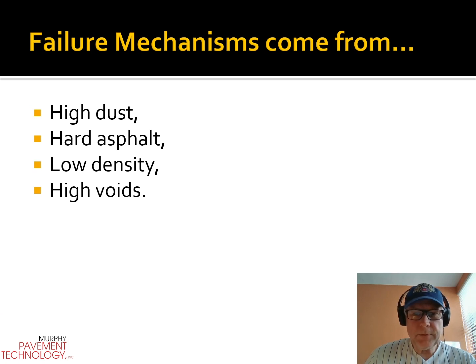So, some summaries again: failure mechanisms, high dust, hard asphalt, low density or poor compaction, and high laboratory air voids. They're all telltale signs of what I typically find when doing forensic work on behalf of people who are challenged with premature failures. And low asphalt content's a relatively frequent theme as well. And most clients are minimizing how much recycle is actually used as well. There's nothing wrong with that. There's just a cost to it. But again, there's nothing wrong with it. Many of my clients will specify mixes have no recycle in the surface courses. Those are their choices.